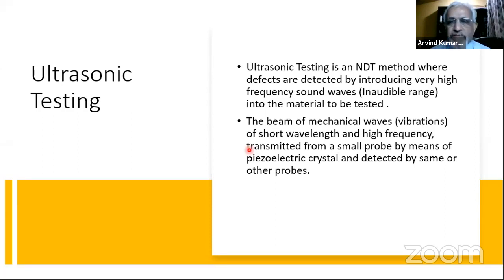the audible range. We do go down to 0.5 megahertz also for certain applications like castings, which have a coarse grain structure, where you use lower frequencies. But generally in industrial application, we have 1 megahertz to 5 megahertz probes which are used.